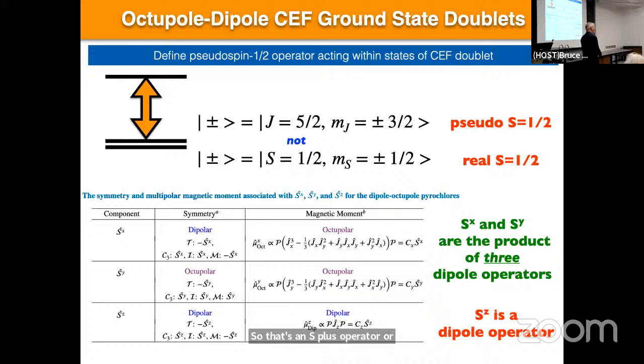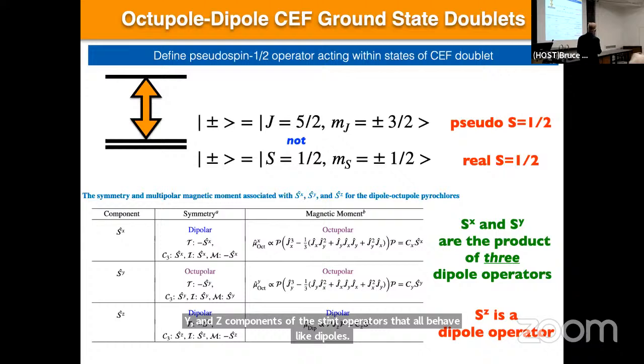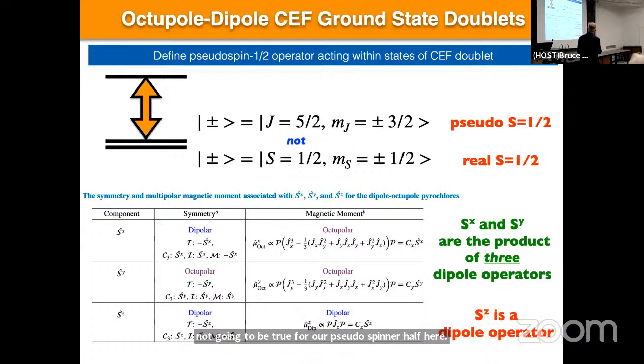Okay, so it's a single S plus operator or S minus operator that connects those two states. Connecting those two states for the lattice gives you the spin waves. So you get conventional dipolar spin waves. Anyway, this real spin a half has X, Y, and Z components of the spin operators that all behave like dipoles. That's not going to be true for our pseudo spin a half here. Actually, the first part of that argument is the same: if I took the expectation value of Jz within the states that make up this ground state doublet, I also get a non-zero expectation value. So the Z component of J behaves like a dipole, okay?